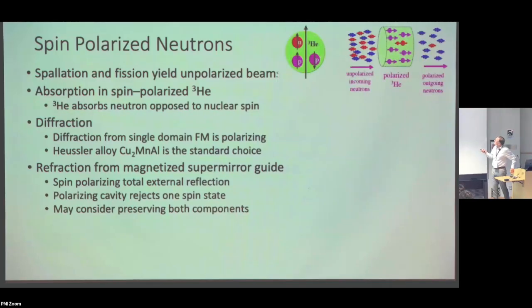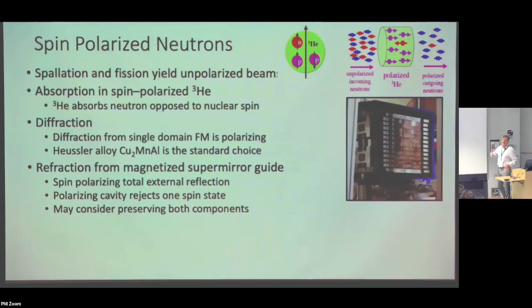We have to polarize the neutrons, which we can do in a number of different ways. We can use helium-3 as a polarized gas. So you can actually polarize helium-3, and then you pass neutrons through, and half of them are absorbed and the other half come through as a polarized neutron beam. That's one way of doing it. That's pretty nice, but you lose half of your neutrons and a bit more. So that's kind of unfortunate.